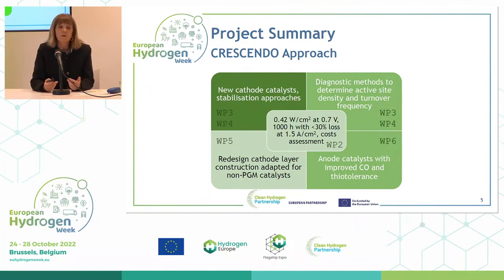So rather than the more trial and error approach that had been used in the past with respect to associating generally a carbon with an iron center, perhaps a hetero element in there as well, nitrogen, phosphorus or sulfur, we also developed diagnostic methods so that we could step by step move forward in determining the site density, the active site density, and also the turnover frequency. So the density of the active sites, the iron sites within the catalyst material, and then the intrinsic activity of those sites.